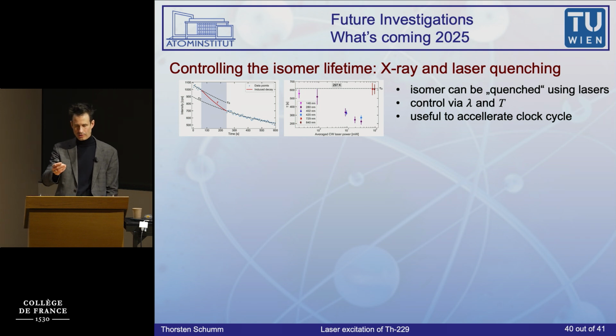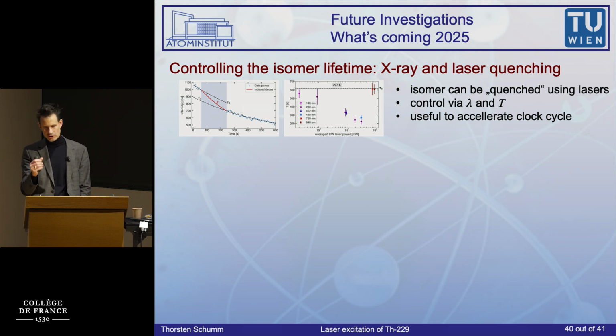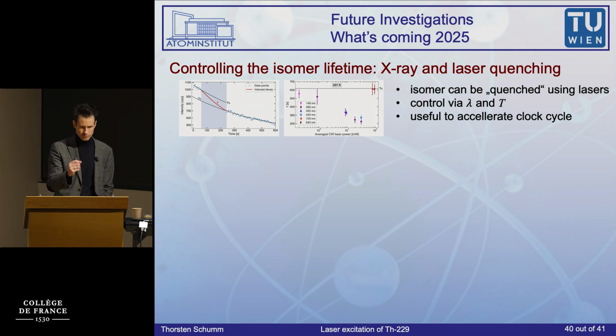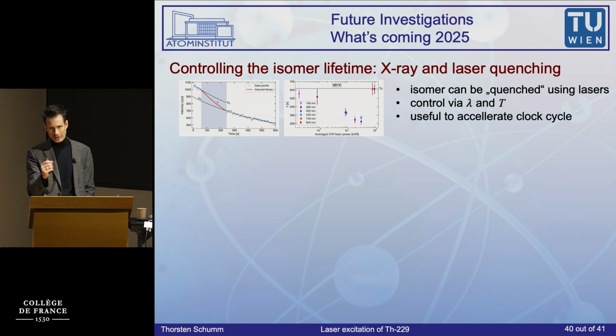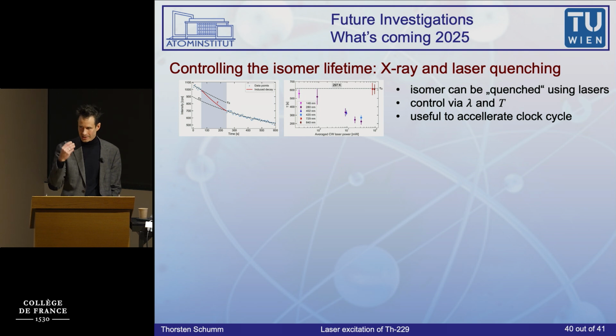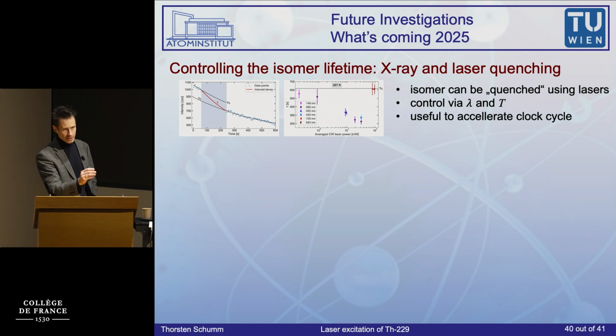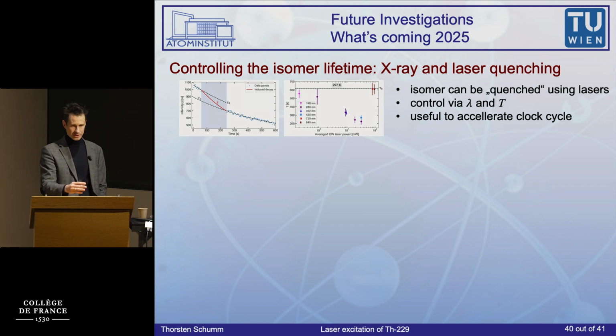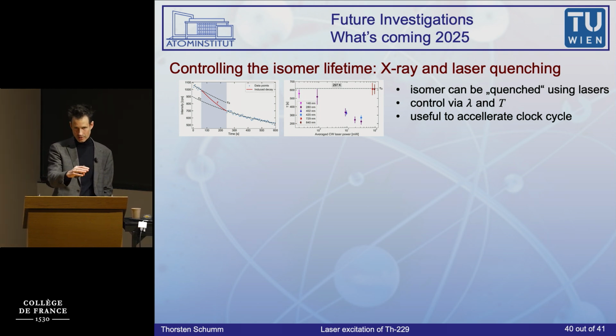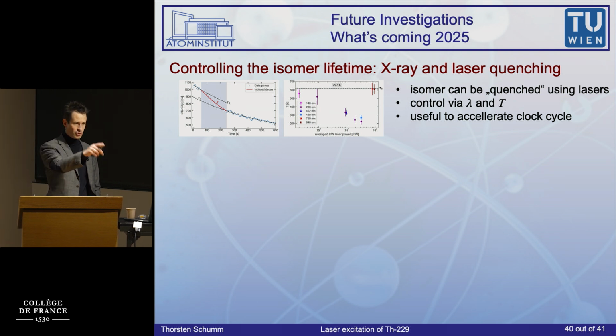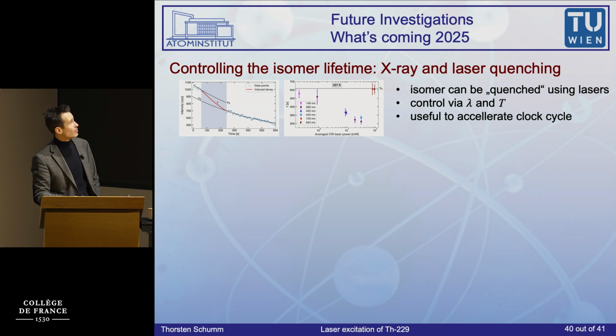You can imagine the excited state nucleus like a little spring. It has a lot of energy and it wants to get rid of this energy, but it can't because there are no electronic states available that are energetically allowed that it can give this energy to. But we can bring electronic states into resonance by laser exciting some defect in the material, and all of a sudden the nucleus sees, oh, okay, I can give my energy in that direction, and then there's a radiative or non-radiative process that we don't know yet that accelerates this decay.